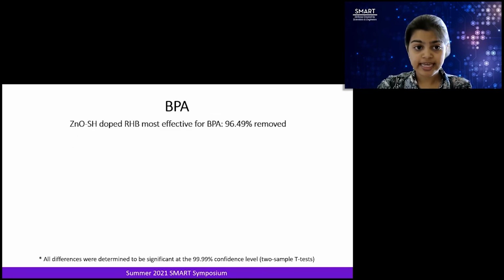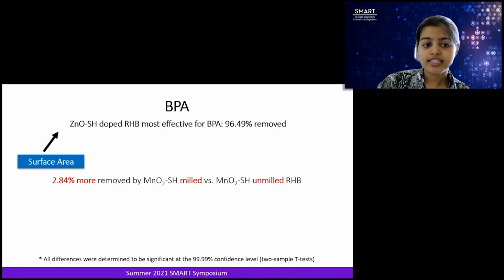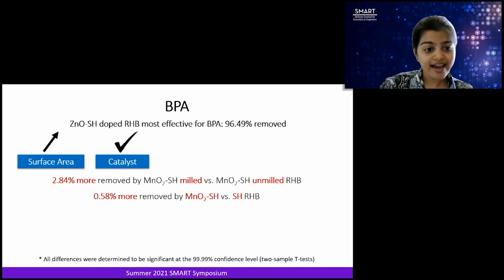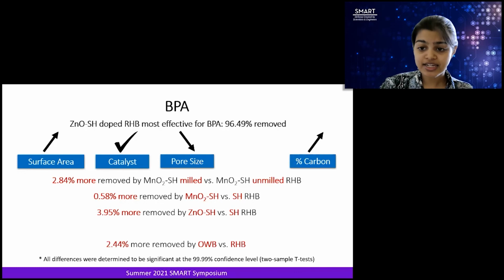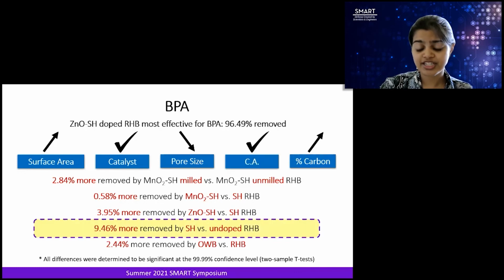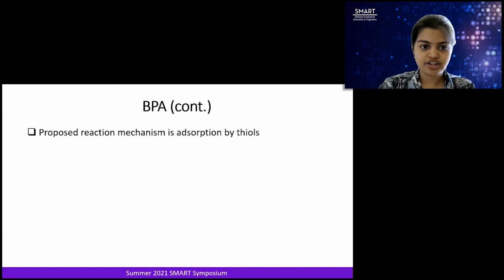Next, let's look at BPA. For BPA, zinc oxide thiol-doped rice husk biochar was the most effective for contaminant sequestration. Zinc oxide thiol-doped rice husk biochar removed 96.49% of contaminants, and high surface area, catalyst presence, decreased pore size, increased percent carbon composition, and complexing agent presence were key for contaminant sequestration. But we see here that complexing agent presence was by far the most important for effective sequestration, and 9.46% more BPA was removed by thiol-doped biochar versus undoped biochar.